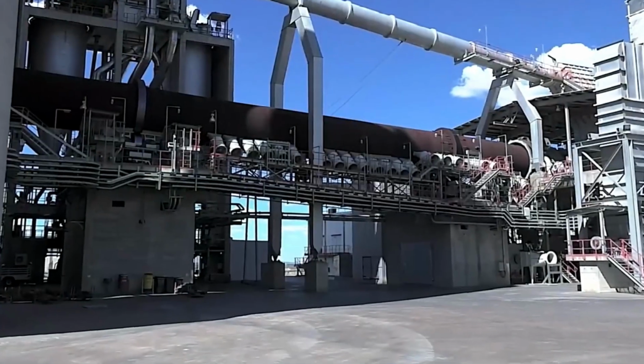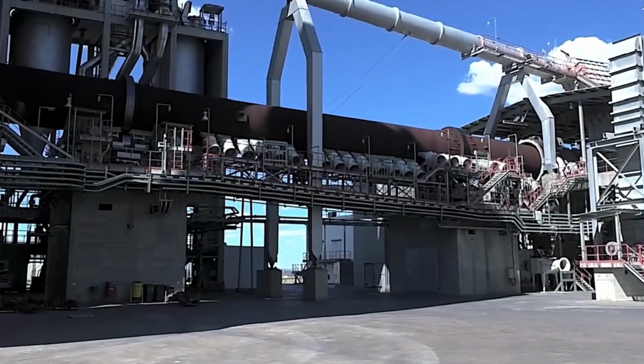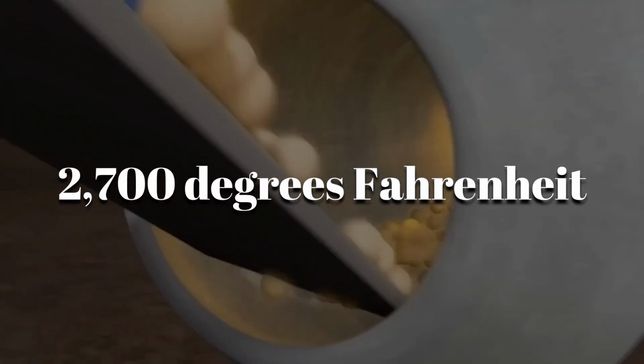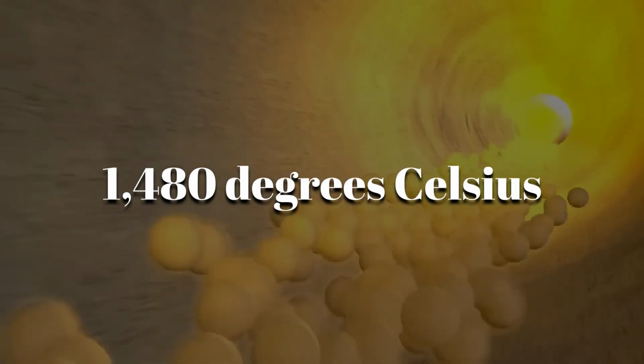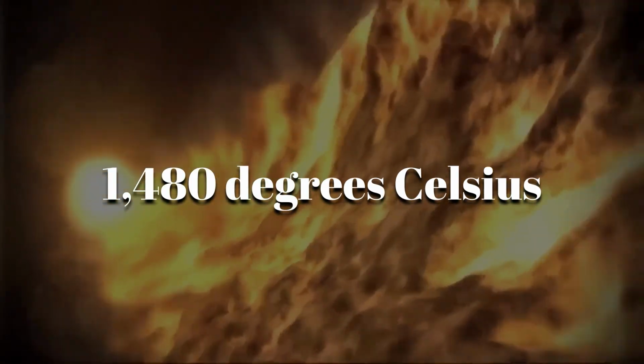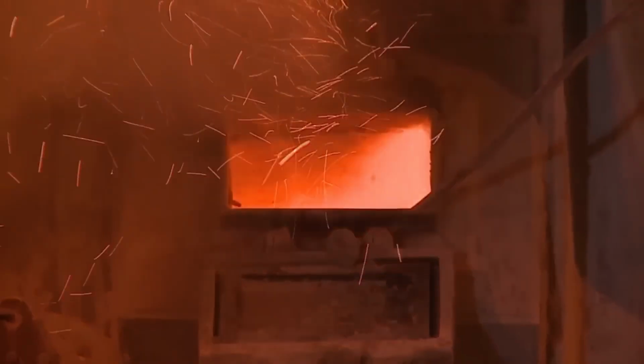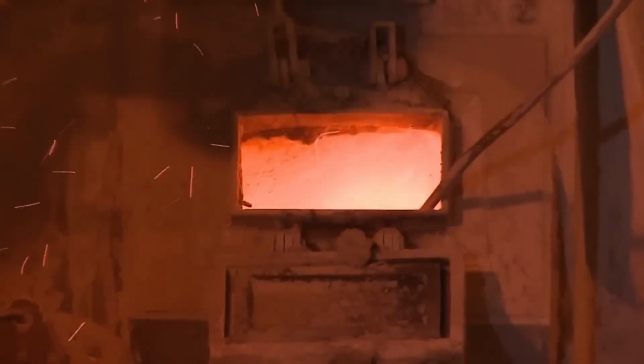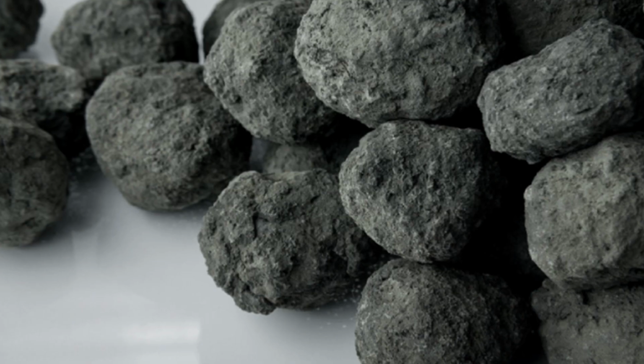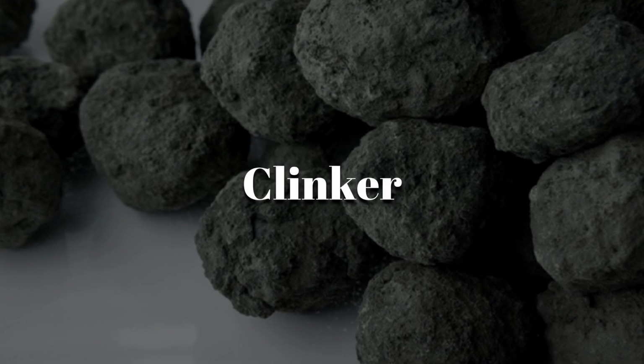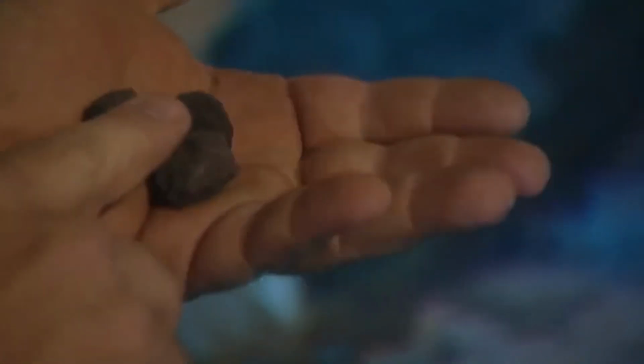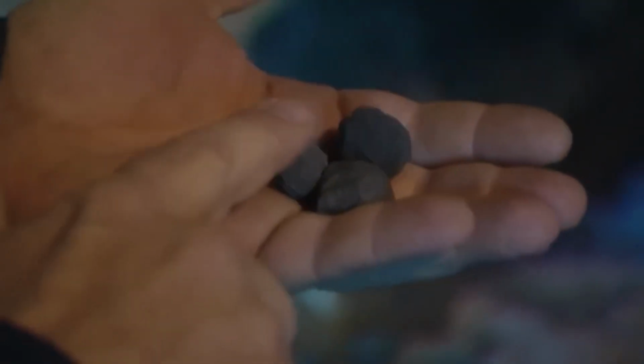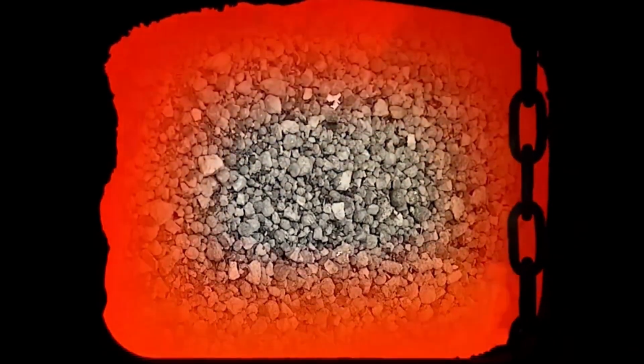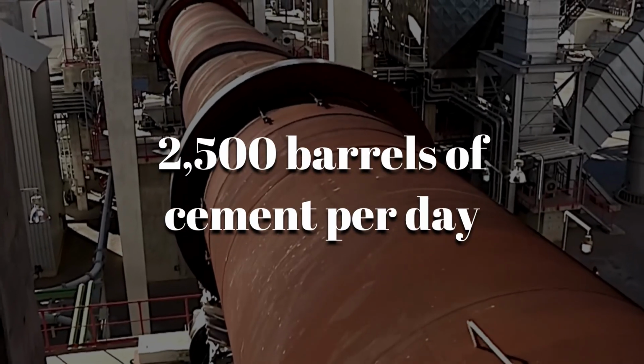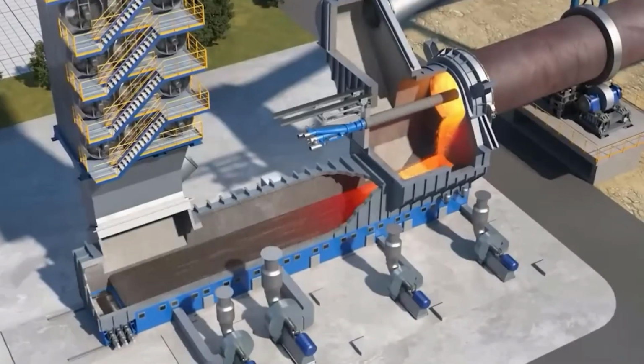As the kilns rotated slowly, the material inside was heated to around 2,700 degrees Fahrenheit, or roughly 1,480 degrees Celsius. At these blistering temperatures, a remarkable chemical reaction occurred, fusing the raw materials into marble-sized pellets known as clinker. These clinkers were the building blocks of true Portland cement. At full capacity, the kilns produced more than 2,500 barrels of cement per day, an astonishing output that kept the